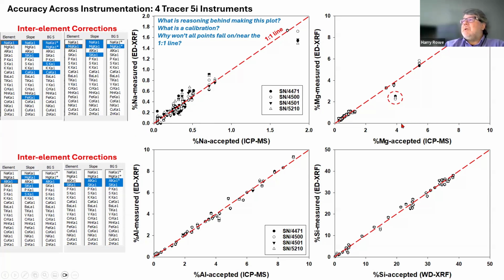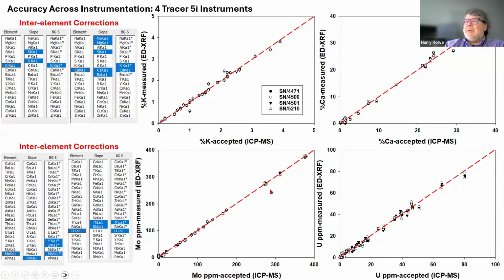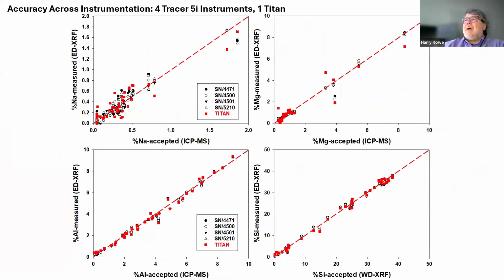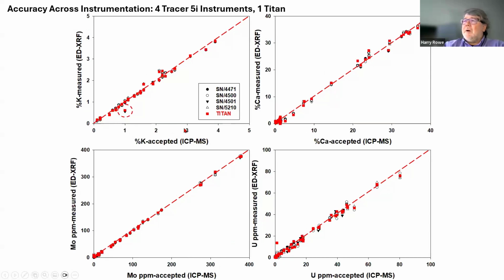Once we get to magnesium, everything's pretty good here, up to over 8%, nicely along the line, except for one sample here. And then aluminum, silicon, potassium, calcium, I'm not going to show all of them. Molybdenum, which is an element that people use to define organic richness, and then uranium. So this is what is achievable across different instruments of the same type, very tight calibration. Another one, we ran an instrument from someone else. It's a Titan made by the same company, but this is what it looks like. Sodium's not as good, but by the time you get past magnesium and into aluminum, very, very good. Okay. So 4 instruments plus that 5th Titan here. Very tight calibration, except for one there.